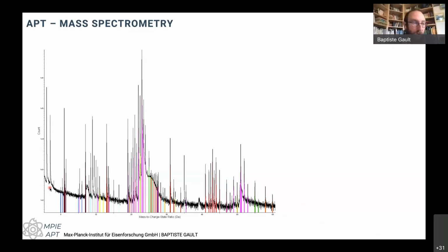So what we have been developing over the past few years are ways to prepare specimens at low temperature. So we go to liquid nitrogen temperature. We can actually do the FIBing at low temperature. So we make these needles at whatever 80 Kelvin or 90 Kelvin. And then we have a suitcase that we can use to transport specimens under vacuum and at liquid nitrogen temperature from the FIB into the atom probe. And then we can do the analysis. So at the moment, there's maybe 5 or 6 places that are equipped with similar suitcases and devices. None of them in India as we speak, but it might happen, I don't know.